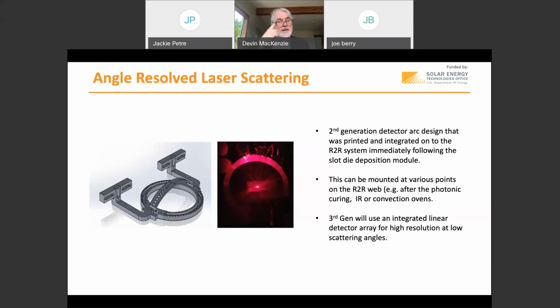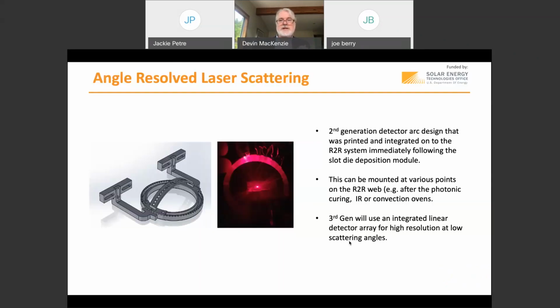And it turns out that now that we've moved to a 790, 800 nanometer laser, there's not much absorption there, and we can hit the film really quite hard. So we have plenty of signal to drive the linear detector array. And so we think that's a really good coupling of TRPL to give you the photophysics, and angle-resolved laser scattering to give you an idea of surface topography related to devices, and both of those can feed back fast. Great. So that's kind of our in situ monitoring.